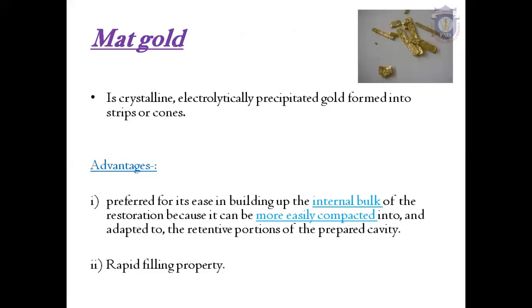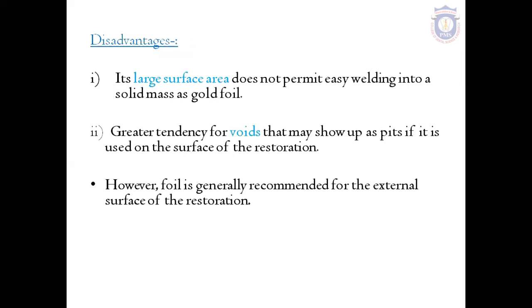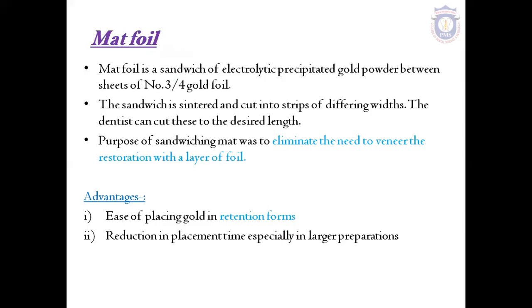Now, matte gold is crystalline, electrolytically precipitated gold formed into strips or cones, and the advantage is the ease in building up the internal bulk of the restoration, because it can be more easily compacted into and adapted to the retentive portions of the prepared cavity, and it has rapid filling property. The disadvantages are a large surface area, which does not permit easy welding into a solid mass, and a greater tendency for voids. Matte foil is a sandwich of electrolytic precipitated gold powder between sheets of gold foil.